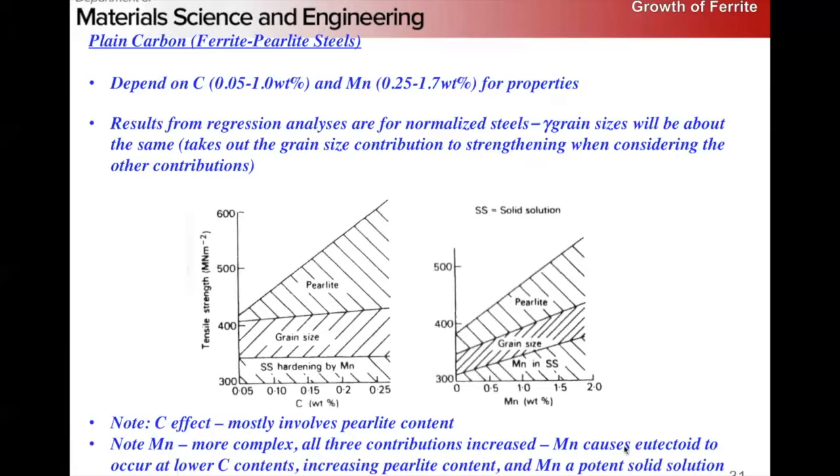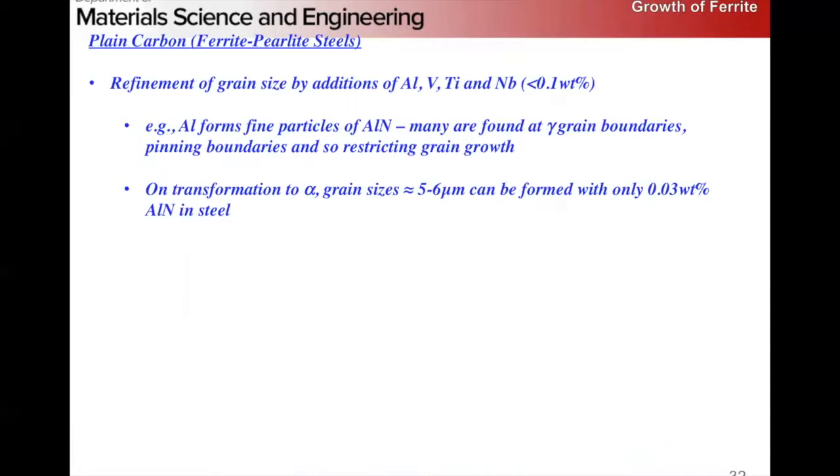Oh, dang it! I put the answer there. I forgot I did that. Manganese, right? We changed the eutectoid temperature, right? So our eutectoid happens at lower carbon content, right? Which means we get increased pearlite formation with the addition of manganese.